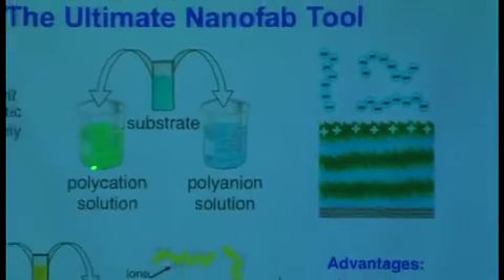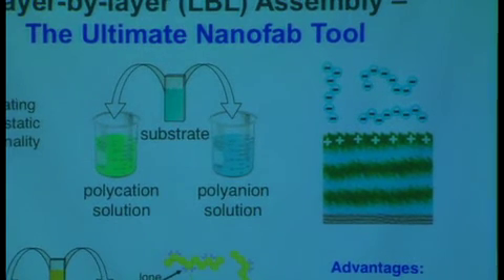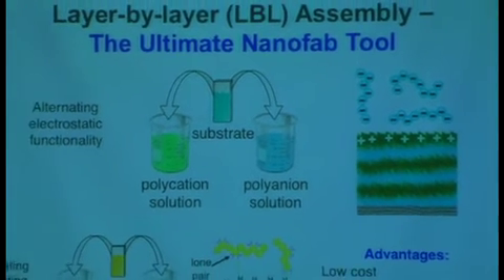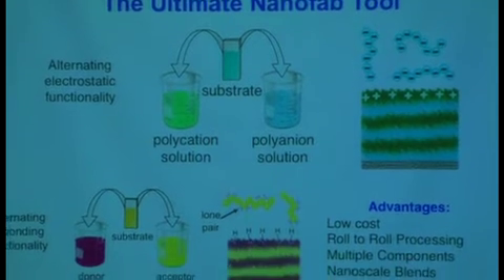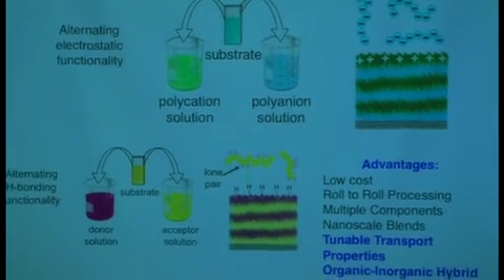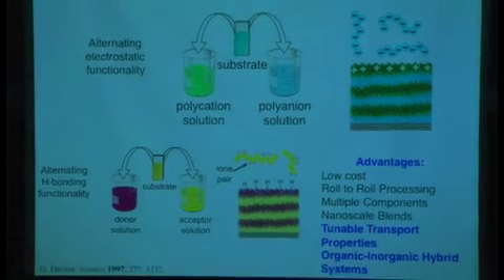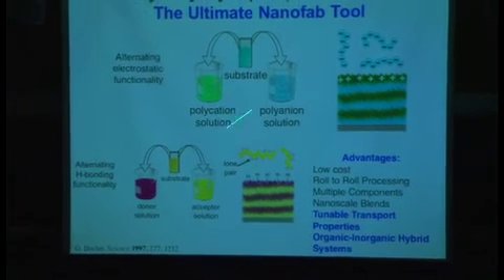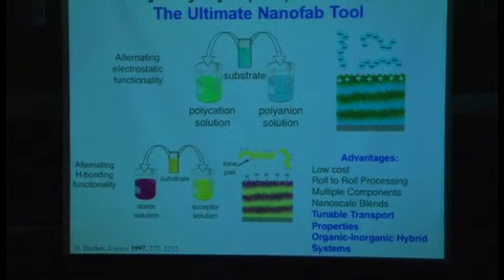In this case, we simply take an initially charged substrate and immerse it into a dilute aqueous solution which contains the oppositely charged polymer. We can then allow adsorption to take place along that substrate until ultimately the surface charge is reversed. At that point, electrostatic repulsion prevents any further deposition on the substrate. And we can rinse the substrate to remove anything that's not truly adsorbed.